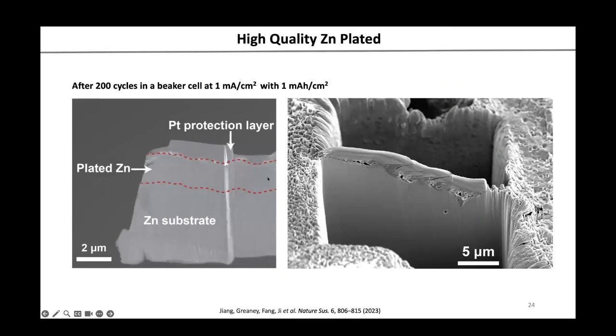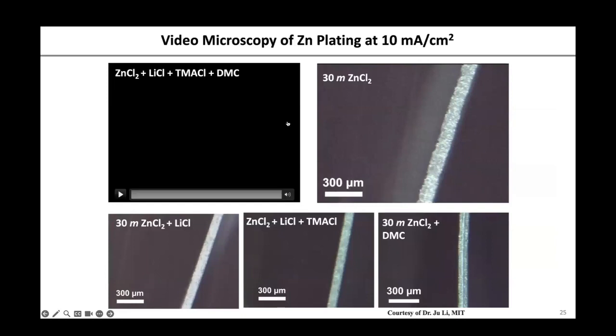Now, look at the zinc metal plated. This is the zinc metal we plated over 200 cycles. Very dense, no pinholes, no cracks. The platinum here is due to the focused ion beam test. You have to put a platinum layer so that you can lift the specimen. That's the cross section. Look at how high the quality of zinc we produce here. And there is a nice video here that I'm going to show you.